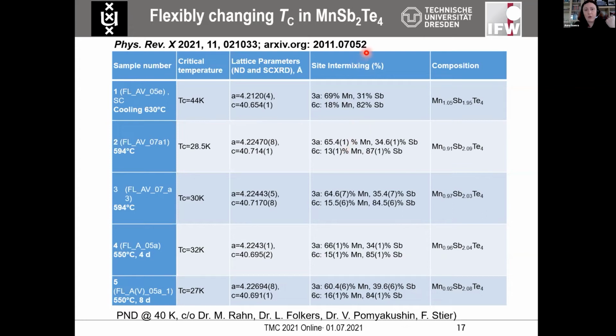Interesting in that respect is the observation made in this arXiv paper by the Rada group and Chulkov group. There they studied MBE grown thin films and they saw overstoichiometric manganese composition. The calculations there predicted that when we only have the exchange of manganese and antimony between the positions, so the overall composition stays the same, the ordering temperature should be at about 20 K. It does not really vary too much with the disorder, but as soon as one adds about 5% of manganese excess, so we are going over stoichiometric, there should be a drastic increase in TC. Wow, seems like it also holds true for our bulk samples. So the ones with the highest TC that we observe may also be overstoichiometric in manganese content.